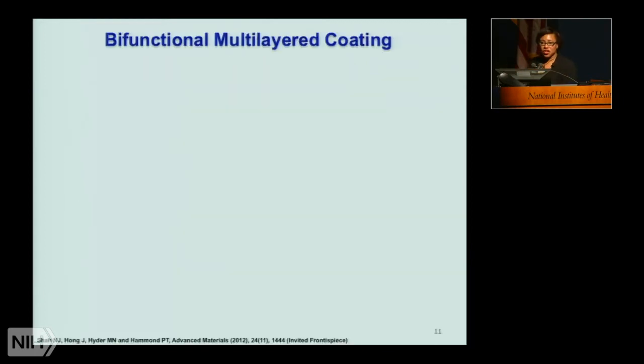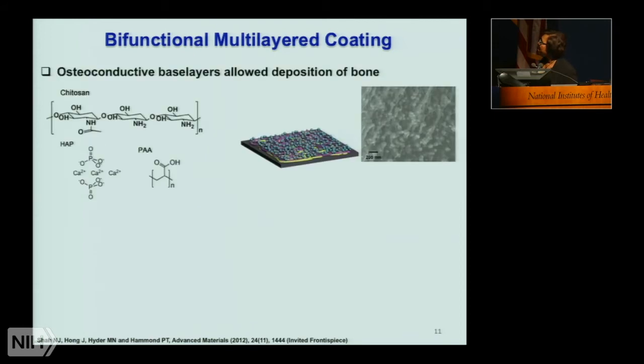We are interested in being able to accomplish this using a singular coating because the common treatment right now is a two-step process in which you essentially remove the implant from the patient, you backfill the empty joint area with these antibiotic beads, which release over a period of 6 weeks or more. You brace the patient, you wait, and then you go back for a second surgery. Clearly, this two-surgery extended hospitalization or immobilization period is not only going to introduce more stress on the patient, but also more cost in the system.